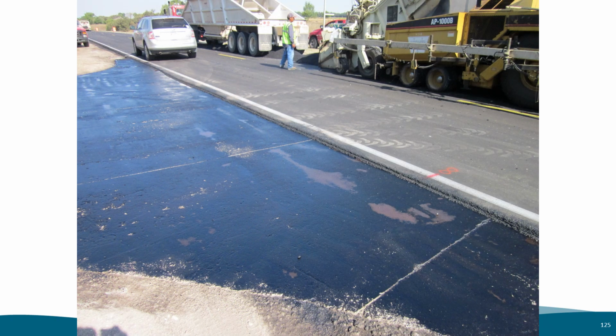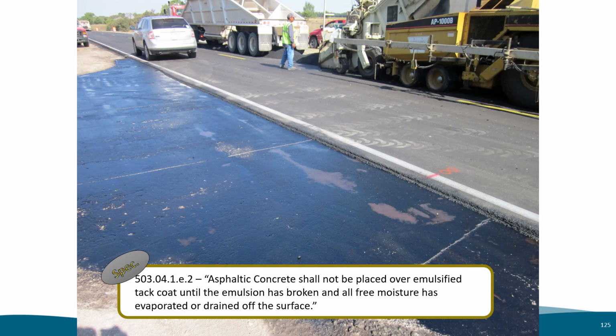Here the contractor has sprayed tack on the next laydown location. The surface is ready to go once all free moisture has evaporated or drained off the surface. As written in the standard specifications, asphaltic concrete shall not be placed over emulsified tack coat until the emulsion has broke and all free moisture has evaporated or drained off the surface.